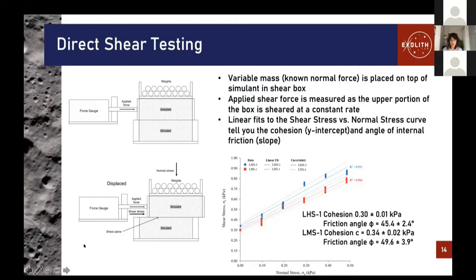The value of cohesion in particular has been something that people have requested from us a lot, because it's an important regolith property, and people want to know, does the cohesion of this simulant match the lunar regolith? So for both simulants, we get around 0.3 kilopascals. The Mare simulant is a little bit more cohesive, but this is reassuring because there's a range of cohesion values reported for the lunar regolith, generally anywhere between 0.1 and 0.7 kilopascals. So that's reassuring.